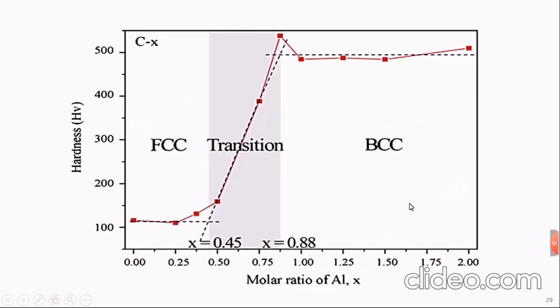Why do you have such specific strengths and this variety of Young's modulus? Because, as I said before, the properties of high entropy alloys can be controlled. As we remember, this is an example of aluminum. When we add aluminum, with little additives increased one by one, it changes the structure completely from FCC to BCC. This means the properties totally changed. So the control of the properties of high entropy alloys is very good, and they can lead to extraordinary properties.